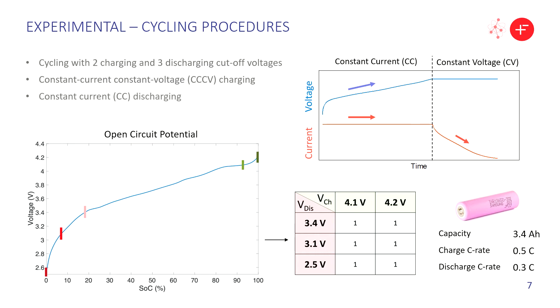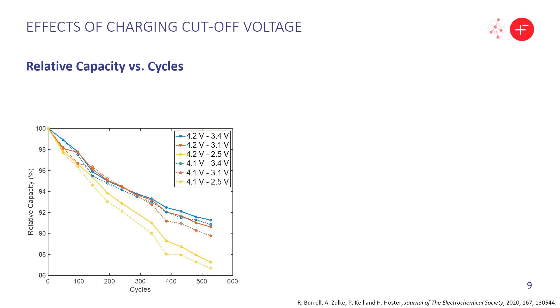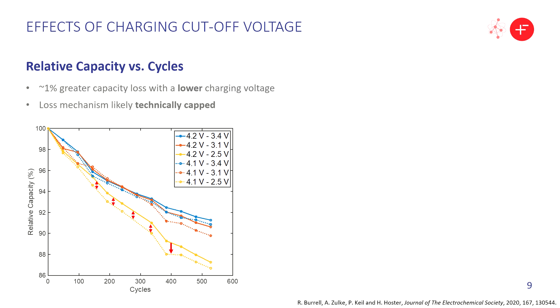During discharging we're using constant current discharging. What we see during cycling these cells in the six different voltage windows looks something like this: here we have our relative capacity over around 500 cycles. Interestingly, we see around one percent greater capacity loss with the lower charging voltage. This is different to what we're expecting and what's often reported in the literature, as normally you expect going to higher voltages during charging to induce a greater rate of side reactions and therefore a greater rate of capacity fade. However, in this case that did not happen. Additionally, once the gap between these two conditions had established it was largely maintained throughout cycling and did not seem to increase or decrease much, leading us to believe that the loss mechanism behind this is likely technically capped.